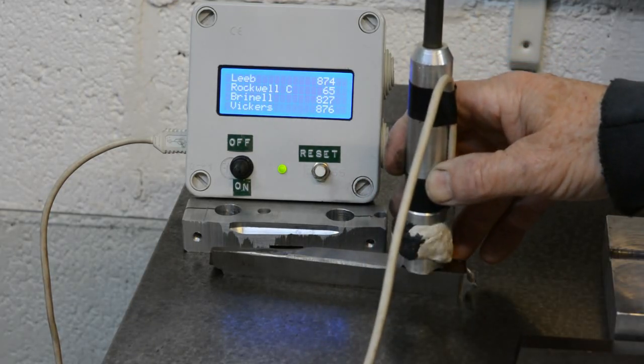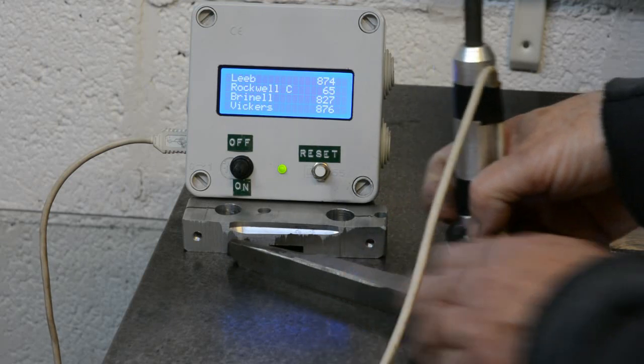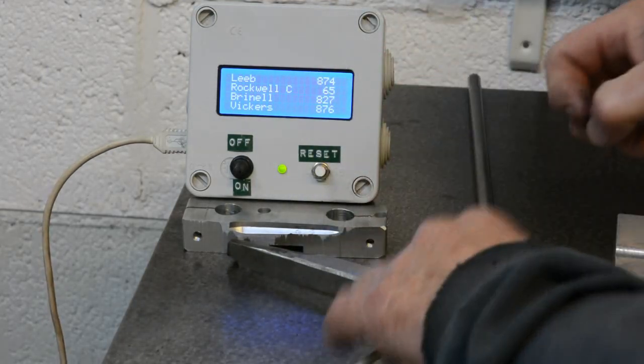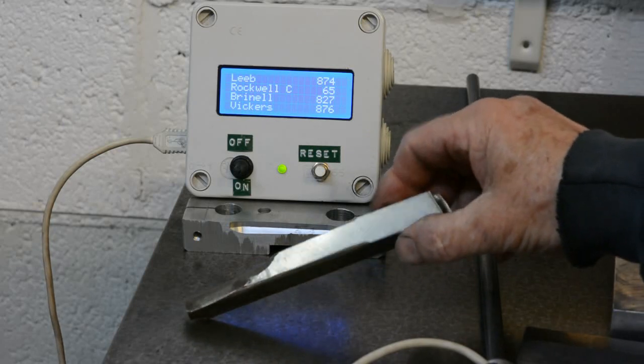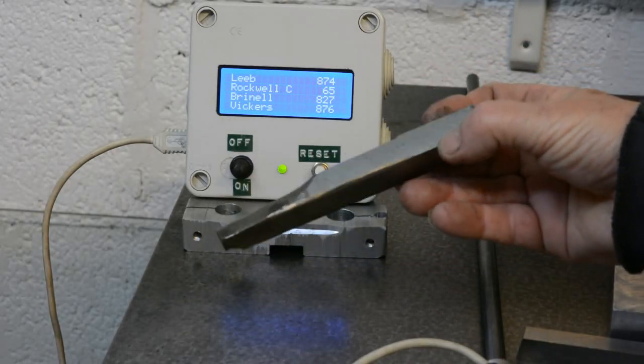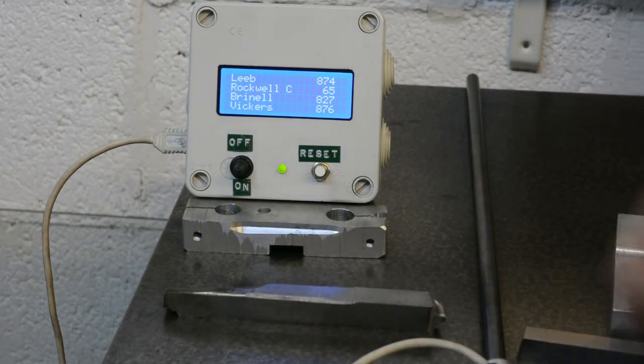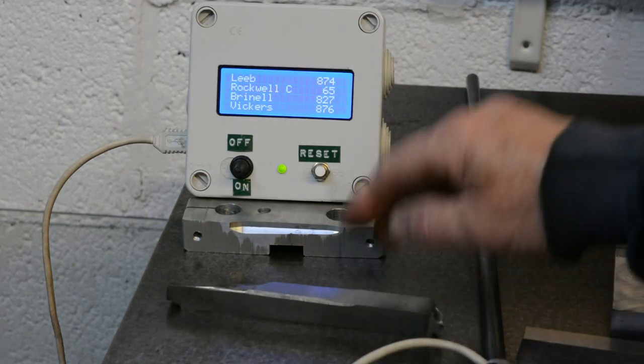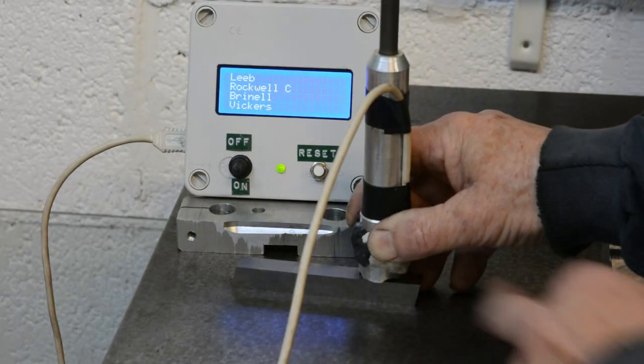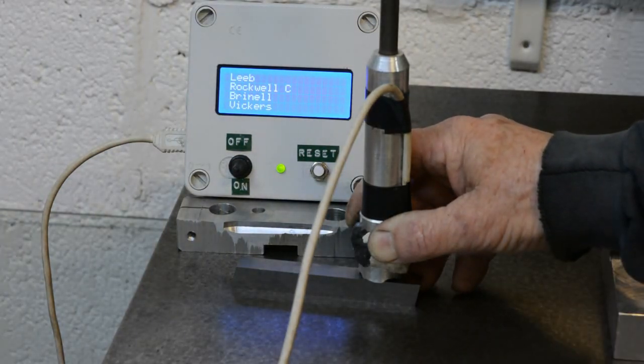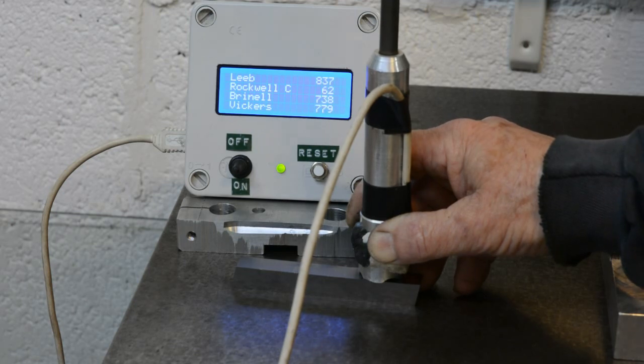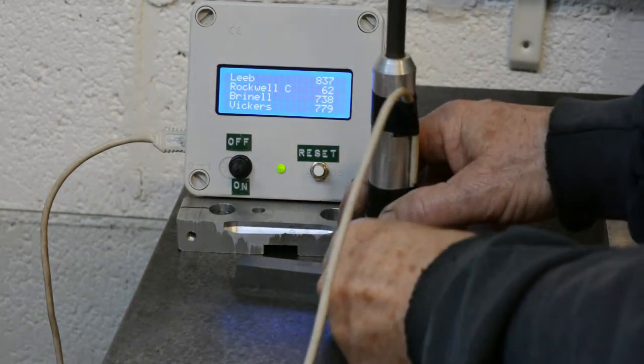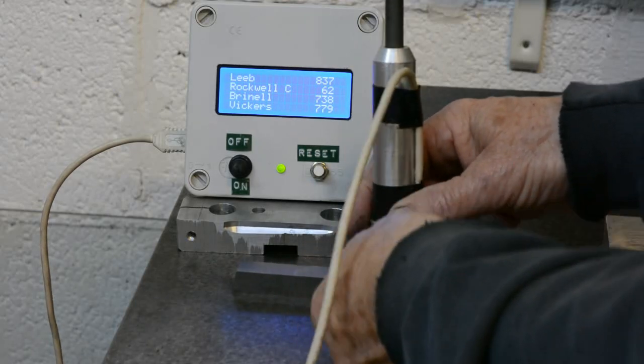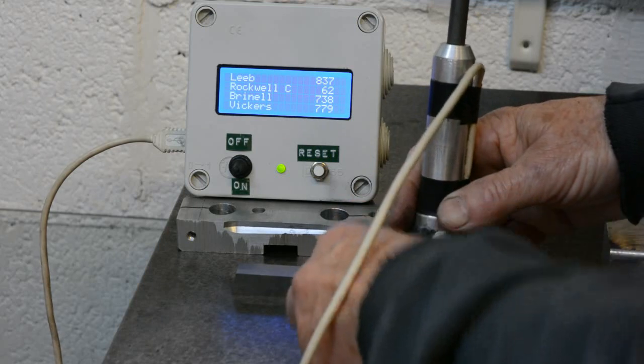What was that? Well, that was my rebound hardness tester doing a test on this piece of high-speed steel, and it showed us on here equivalent of a Rockwell C of 65, which is about what we would expect for something like that. Let's try again with this other piece of high-speed tool steel. And we get 62. It's a little bit less than the other one, but they all vary somewhat.